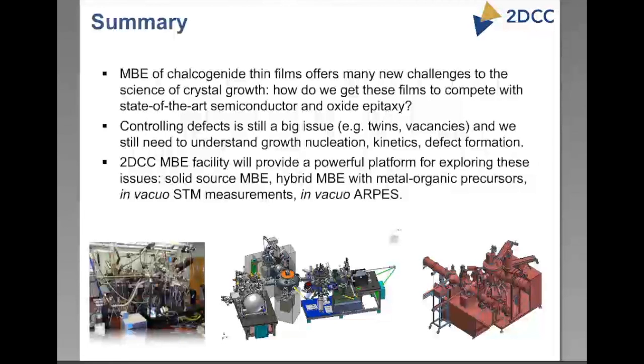And so they seed the growth of the indium selenide on a very thin layer of bismuth selenide. And surprisingly, and I think it's not speculation, they have clear cross-sectional TEM images. When they heat up the bismuth selenide and indium selenide combination, the bismuth selenide apparently just diffuses through and evaporates. That leaves the indium selenide in a fairly good crystalline form on the sapphire, and that provides the basis for growing the rest. I don't know if it's in the paper: have they tried depositing indium selenide at low temperature and heating it up? I don't know that they tried. I honestly don't think they mentioned it in the paper.